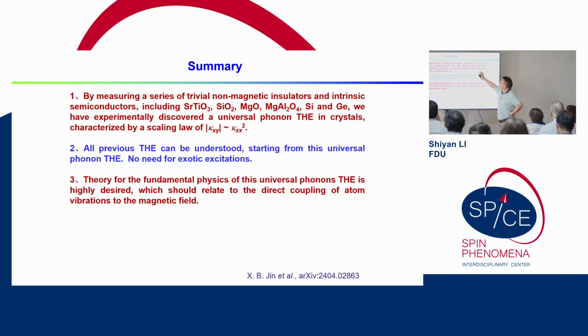So basically, it's very, very striking. We started with chiral phonons, and step by step we went to MgO, to silicon, and finally discovered this universal phonon thermal Hall, with this scaling law. And now we hope all these previous results can be understood. You start from this phonon thermal Hall, then if it's not trivial, you examine the effect from the magnetic environment and from impurities, and basically there is no need for exotic excitations.